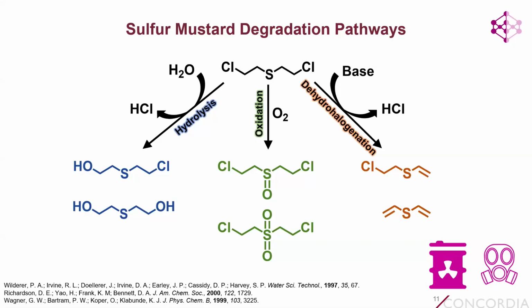And so we choose to focus on the oxidation pathway because ideally we can just use molecular oxygen as an oxidant. But you also have to be careful with this pathway as well because it has to be selective to generate the sulfoxide. Because if you over-oxidize this compound and you generate the sulfone, this is almost equally as toxic as sulfur mustard itself. So it's the selective oxidation of the sulfide that is key.